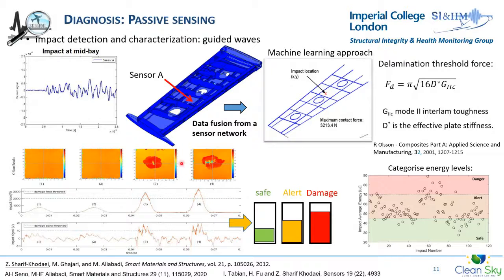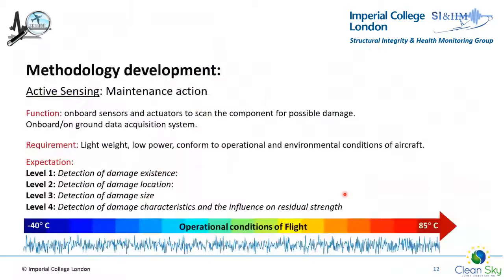So really, by looking at it at this level, we can categorize the impact into safe, alert, which is the region close to initiation of damage, and also a red signal, which means okay, something definitely has happened and you should ground the plane and go to the next level, which is active sensing, the damage detection. So localize the damage and categorize its size and severity if possible as well.